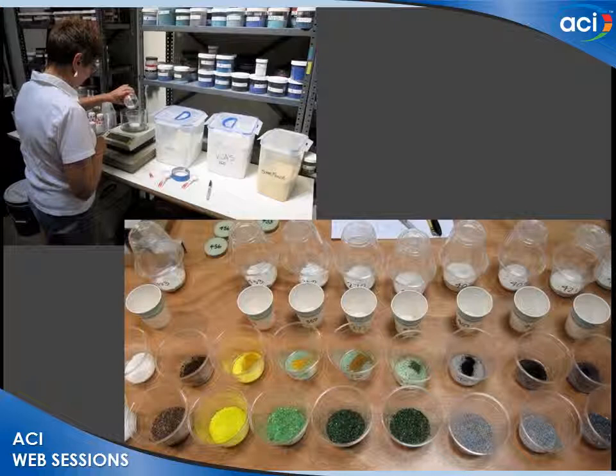It took about 2 days to pre-batch all the materials for one 3-foot by 5-foot panel. We had to get a special scale because the pigments had to be measured sometimes to the 100th of a gram in order to keep consistency. Now these mixes, we had 9 different ingredients. We used 25% pozzolan in addition to a white Portland cement. We often had 2 or 3 colors of glass as well as 2 different pigments in there. And we used a superplasticizer. Our water-cement ratio was about 0.33, which is surprising, but we can do that with our modern chemicals.